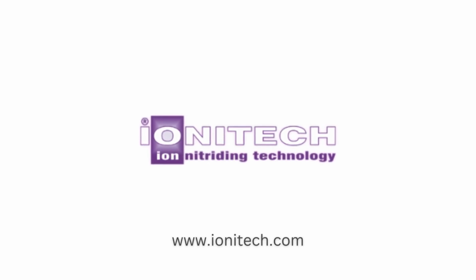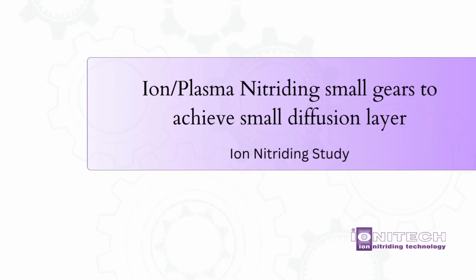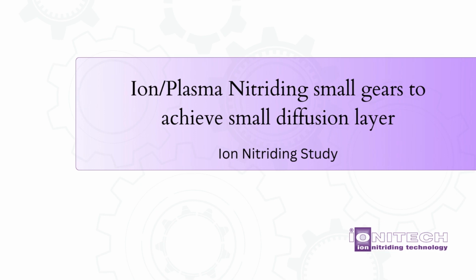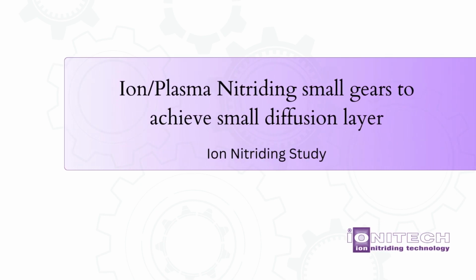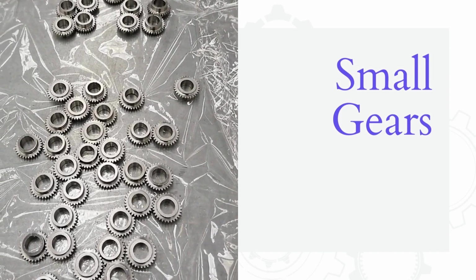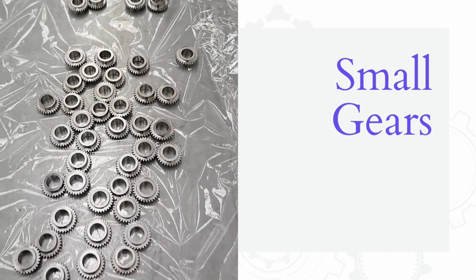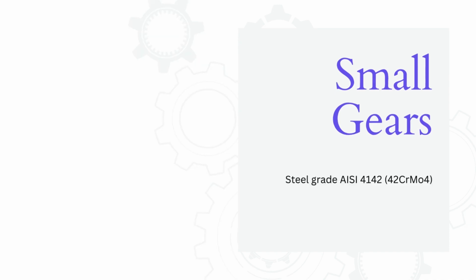We at Ionitech receive different tools and parts for nitriding from different industries, and some of them pose challenges and requirements that stand out. We got a very interesting requirement, nitriding small gears made of steel grade 4142, with a request to achieve a very small diffusion layer of less than 100 microns depth.